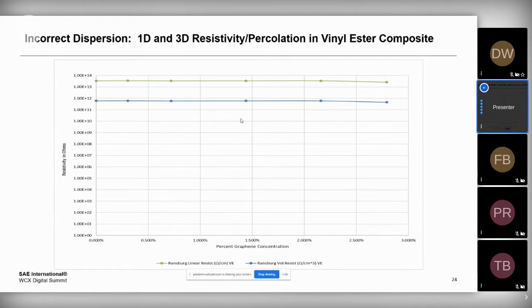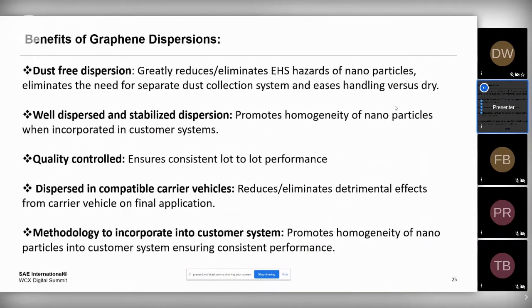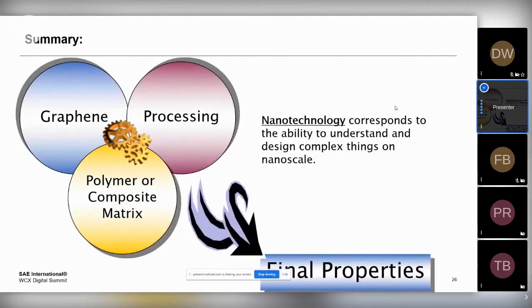In the other case, if you do not have it dispersed, it will take you a much higher loading before you achieve a similar type of percolation threshold. In this particular case, we're going up to above 2.5 and 3% before we start to see any type of percolation at all. So the characteristics that you have in your system, in terms of dispersion, are really important, and how you incorporate it is important. Some of the benefits of using the dispersion are to give you a dust-free dispersion, but really the central issue is the type of graphene you're using, the type of processing you're using for it, and the types of polymer and composite matrix that you're using it in. These things all have to fit and work together.